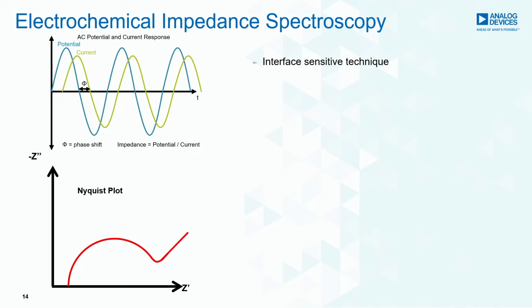It's a very interface sensitive technique because the impedance reacts to the changes that are at the interface, and the reactions are going across the interface. Usually what you do is you scan the frequency of the AC potential that you apply, and then you plot the impedance for each frequency. And then you have to find a way to plot this huge amount of data.